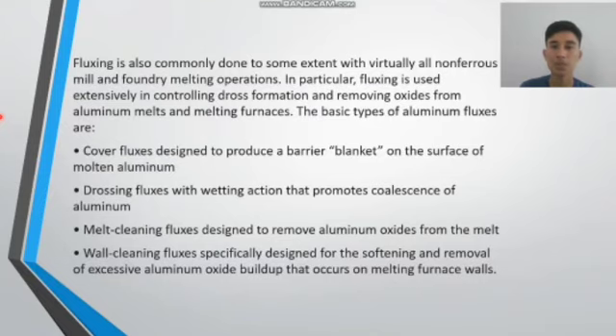In particular, fluxing is used extensively in controlling dross formation and removing oxides from aluminum melts and melting furnaces. The basic types of aluminum fluxes are cover flux, designed to produce a barrier blanket on the surface of molten aluminum; next, drossing fluxes with a wetting action that promotes coalescence of aluminum; melt cleaning fluxes designed to remove aluminum oxides from the melt; and wall cleaning fluxes specifically designed for the softening and removal of excessive aluminum oxide buildup that occurs on melting furnace walls.